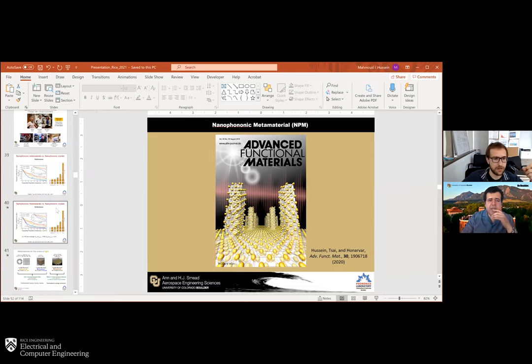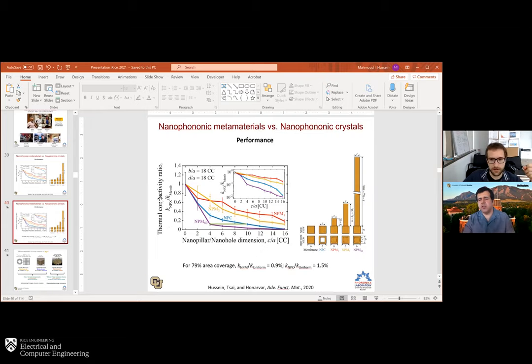Indeed. As I was saying, this picture really answers your query, Alessandro. As we increase the coverage area, that's exactly the x-axis. Whether we're looking at a hole or a pillar from the top, that's the width of the hole or pillar. The entire size is roughly 18 conventional cells, and the biggest size possible here is 16. So this is almost fully covered from the top by pillars, with extremely small distances between them. That's where you get the strongest reduction, as I was explaining earlier, because you get more resonances and more of the effect.